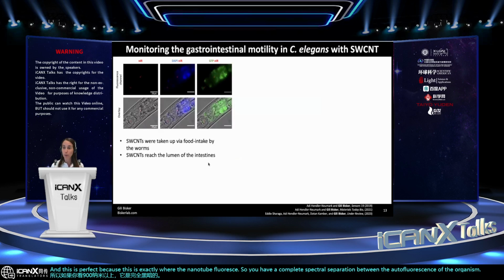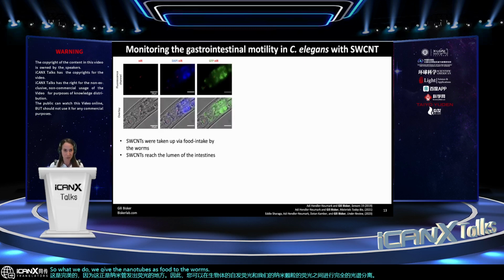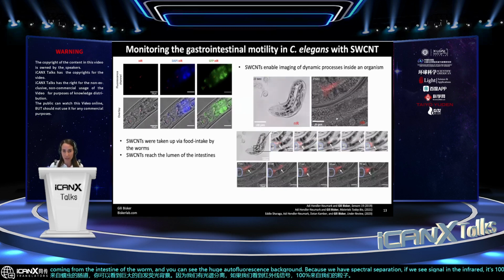So what we do, we give the nanotubes as food to the worms. They basically eat the nanotubes, and they end up in the lumen of the intestine. You can see here the near-infrared fluorescence of our nanotubes coming from the intestine of the worm, and you can see the huge autofluorescence background. Because we have spectral separation, if we see signal in the near-infrared, it's 100% coming from our particles. So these particles can be used to monitor, for example, the gastrointestinal motility in C. elegans, using the near-infrared fluorescence. And of course, we can quantify it and extract biologically relevant parameters of the contraction of the GI tract of the worm.